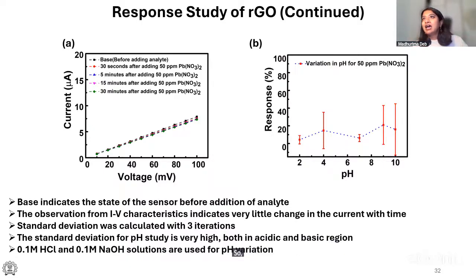These are all lab studies that I'm showing right now. And I also wanted to show you this small IV characteristics of the base material before I go to the modification of the material. You can see the IV characteristics, it's not changing even after 30 minutes. It's just overlapping with one another almost.